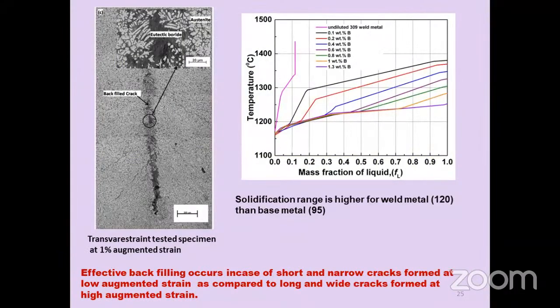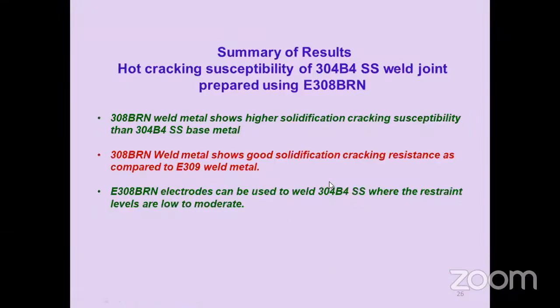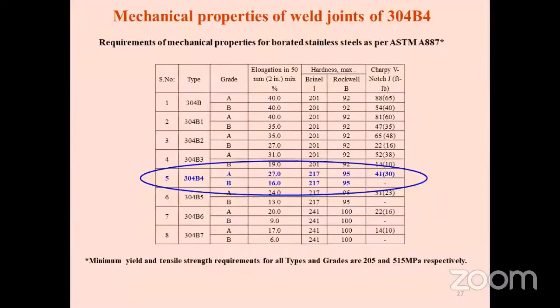This is because, as I explained, the volume of eutectic liquid that forms varies with boron content. With a higher amount of boron, we have a large amount of liquid fraction. With decreasing boron content, we have decreasing eutectic liquid, which is not sufficient for backfilling to occur. So now we have seen that borated electrodes also serve the purpose, but they are not very highly resistant to hot cracking.